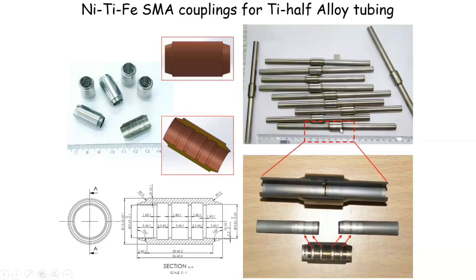And what the nickel titanium shape memory alloy does is that it's very easy to deploy. You put it in liquid nitrogen, open it up, and then when you apply it to the tube, it will sort of self-swage. It's heat shrinkable, and it will swage these rings onto the tube. It can be made very strong. It's a very strong material. It will swage onto the titanium.